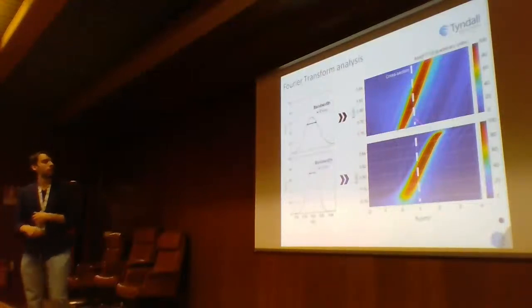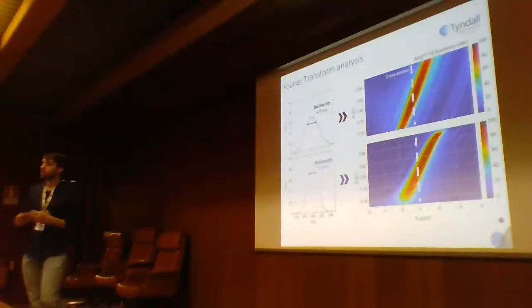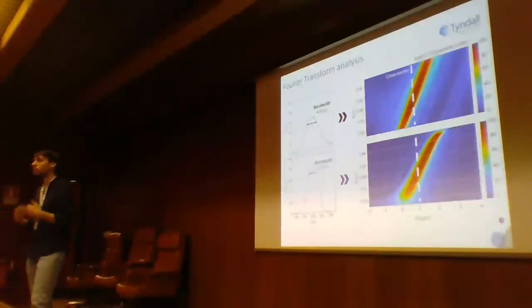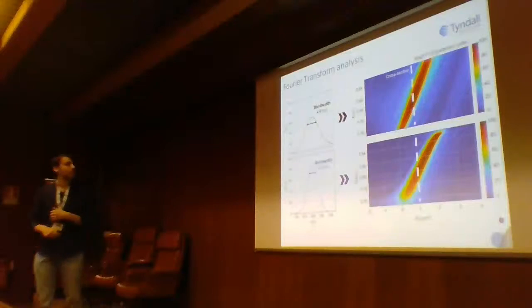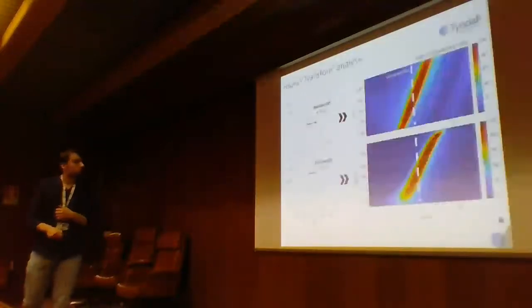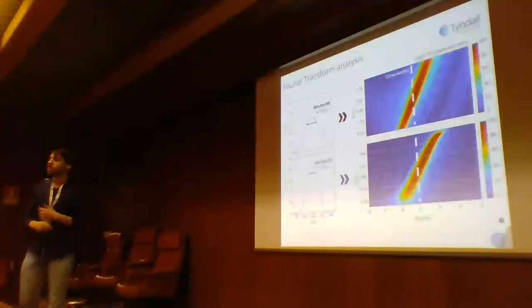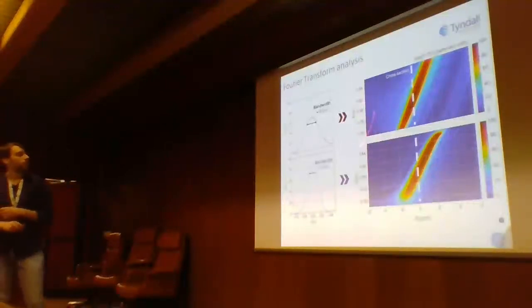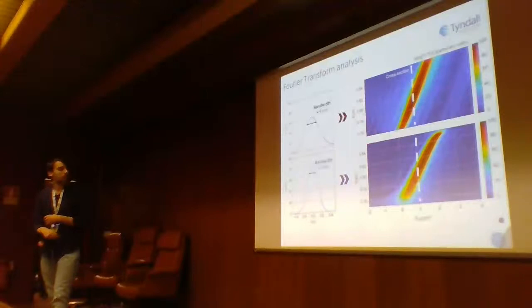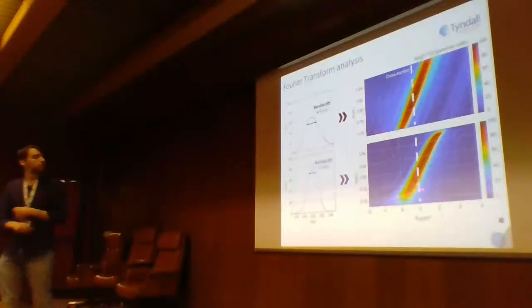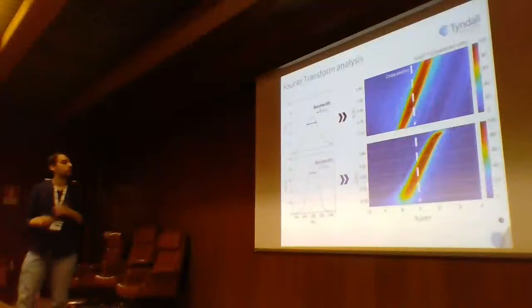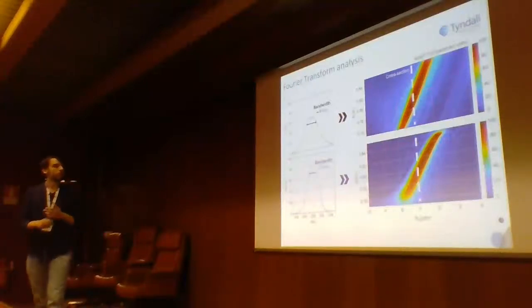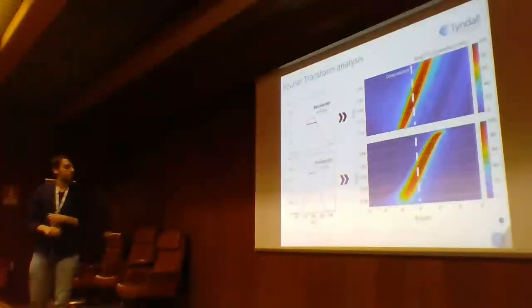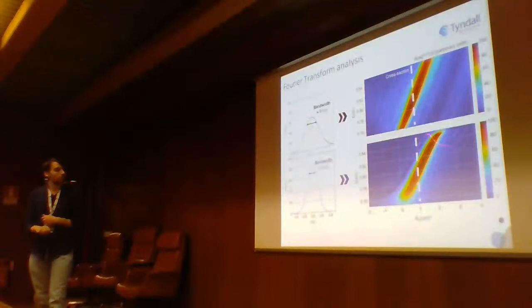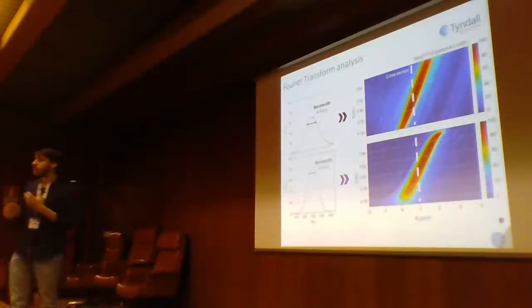So how can we study this bandwidth reduction? The first thing that we can do is to collect the emission of the grating coupler, because this type of structure can also be used to upcouple the light from the chip, and to look at the Fourier transform of the emission of the grating. And so we can get the spreading in the energies in terms of the k, so the wave vector. As you can see, first of all, the uniform grating coupler has a uniform Fourier transform if we divide the plot into two parts. Instead, the non-uniform grating coupler, as you can see, has a thicker region here and a thinner part here. So in terms of the energy, it's acting like a filter.